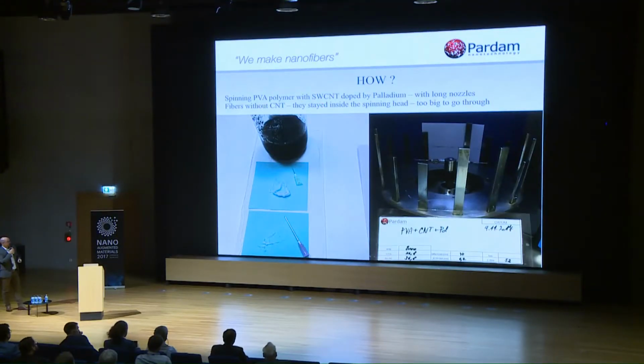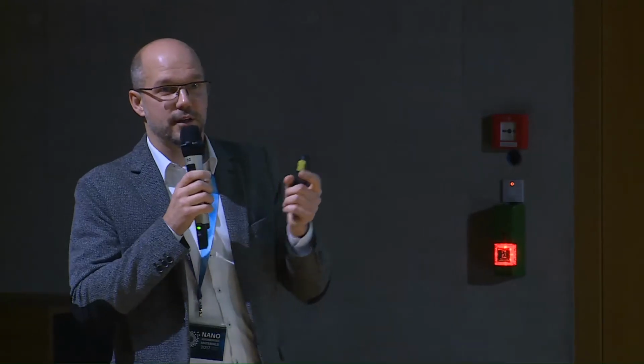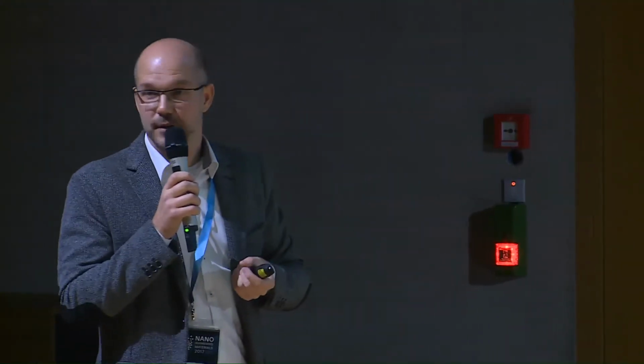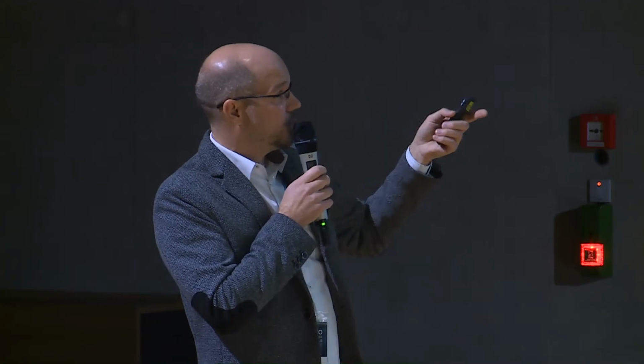Basically, you can see the laboratory spinning tool which we are using for fiber development. It's a simple tool which has a small container and 2 nozzles. Through the nozzles we are spinning out the fibers. We collect them on the collector and then analyze them. Actually, what you see, we used long nozzles or syringes,